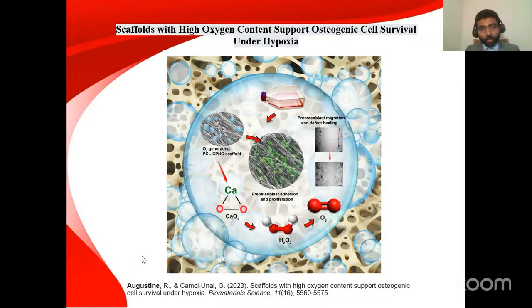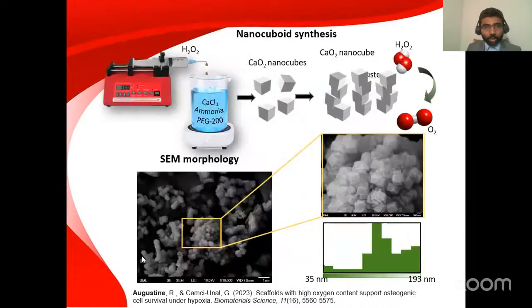Then when we incorporated this oxygen generating material in electrospun scaffolds and used it in hypoxic condition, without oxygen, we found that pre-osteoblast cells can proliferate very well and survive in hypoxic condition and help in bone regeneration. This was the basic approach using calcium chloride and ammonia. In the presence of PEG, we synthesized calcium peroxide nanocubes, which have a cube-like structure, and the SEM morphology shows that cube-like structure.